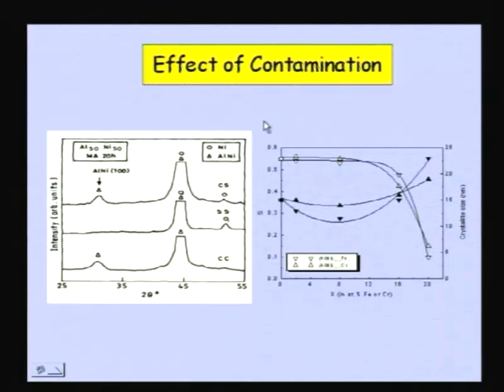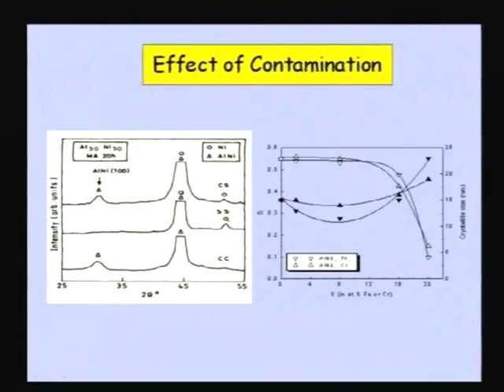And this is the effect of contamination. We know that contamination is one of the major problems by ball milling, but sometimes contamination can be useful. We have talked about it at some point of time. Here contamination can lead to what is called disordering into a compound. If you ball mill NiAl in tungsten carbide, you get an ordered superlattice reflection, but if you ball mill it in a stainless steel, you will never get a superlattice reflection. That means it is completely disordered. That is because the iron, coming from the balls and the container, goes into the NiAl and reduces the ordering energy, and because of which the ordered NiAl completely becomes disordered. And once it becomes disordered, it becomes ductile.